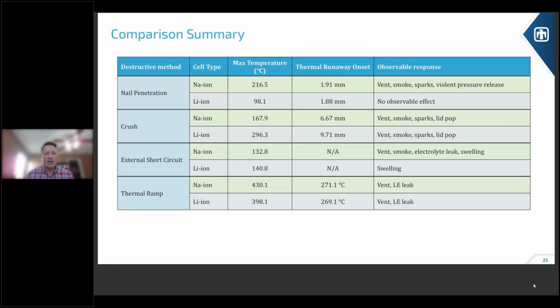So just in summary, we had a nail penetration, which is a pretty standard abuse test. We got a hotter temperature with sodium ion, and we got a much more violent response. If you recall, this is the one that broke the nail off the fixture. Then we did a crush test. In the crush test, the lithium ion did get quite a bit hotter than sodium ion. However, the sodium ion required less crush depth, so we went into the cell a lesser distance for the sodium ion to get that runaway initiation.